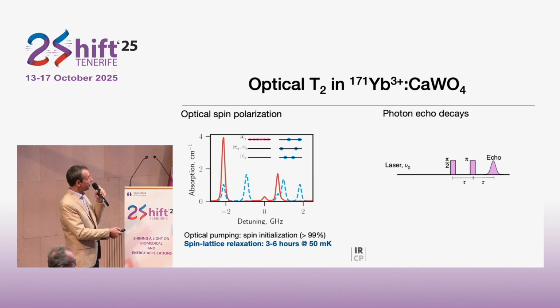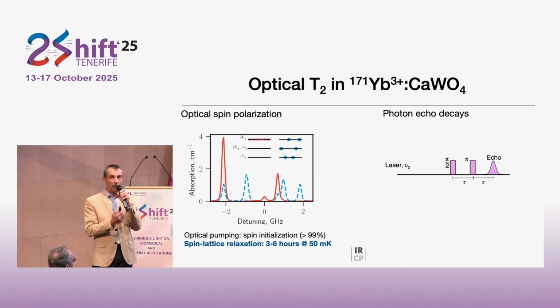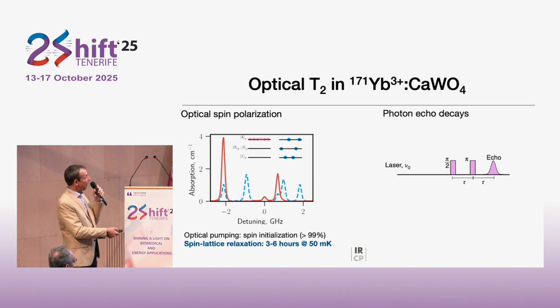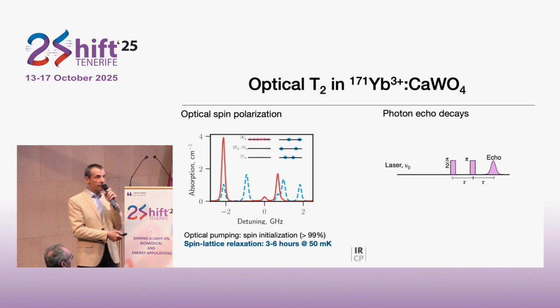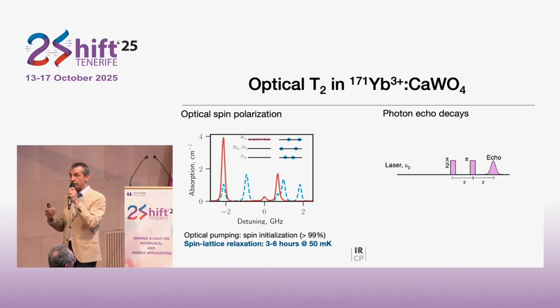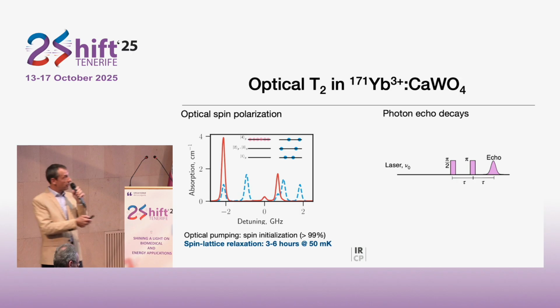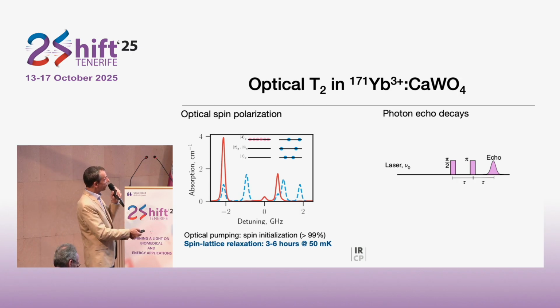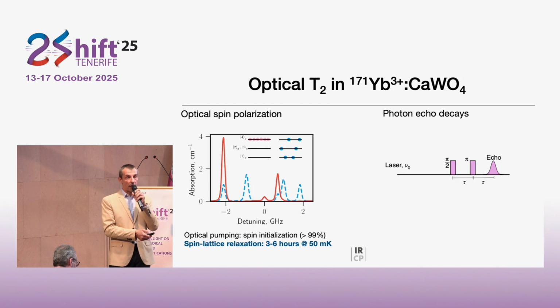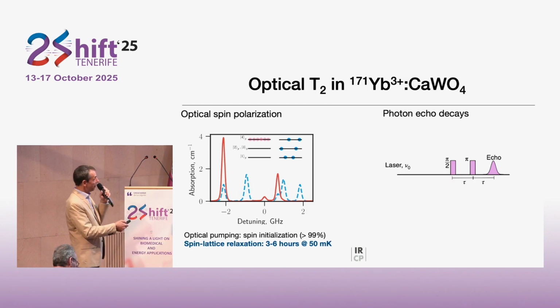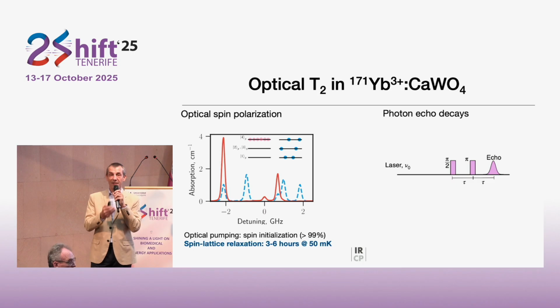After this delay, we send a second pulse, which will reverse the time evolution of the quantum states. And so after the same delay as we had between the first pulses, the quantum states of all ions are back to the initial situation. And at this time, we will observe a collective emission of light, which is called the photon echo. The point here is that only the ions which have no perturbation from the first pulse to the echo emission can actually participate in this emission.